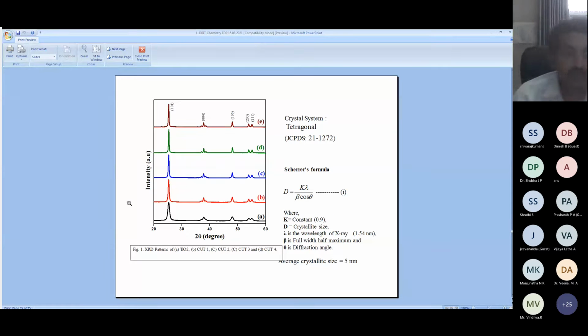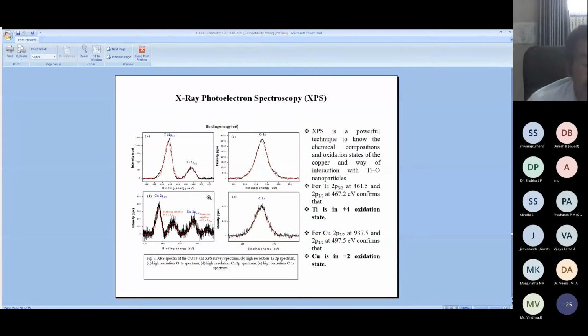When we took the XRD, this is pure TiO2, and these are the copper doped TiO2. Because of the presence of only 1%, 2%, there is no change in the XRD pattern, right? There is no extra peak due to copper, but there is a small shift in the highest intense peak of the XRD. Of course, we have mentioned that in a paper. The small shift in the XRD indicates the inclusion of copper, Cu2+, in the material. Now when we did XPS, it says that titanium is in the +4 oxidation state and copper is in the +2 oxidation state. That is nothing but Cu2+, right?